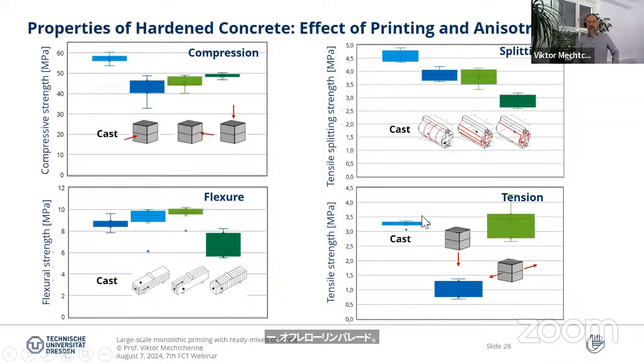And most pronounced, of course, is the difference in the direct tension. So this is tensile strength. And you see that when we test perpendicular to the joint, so in this direction is tension, then the values are much lower than in the case of the cast specimen or the specimen which is printed but tested in the other direction. So it still might be a good enough value, but this is what you should know. And if it's of interest to have the strength, specifically also tensile strength, in different directions, then it needs to be tested.